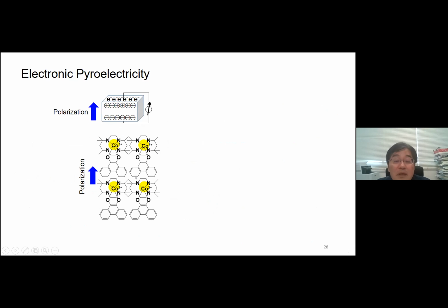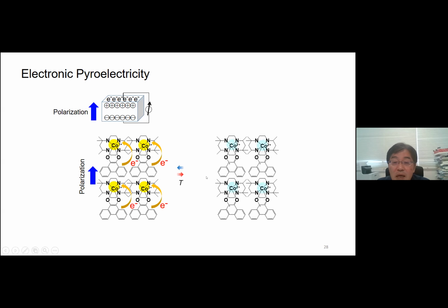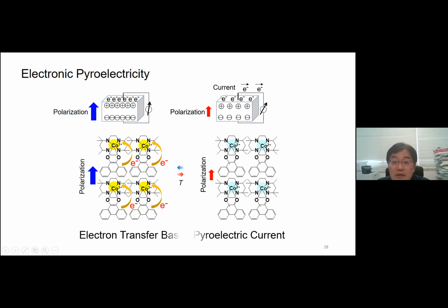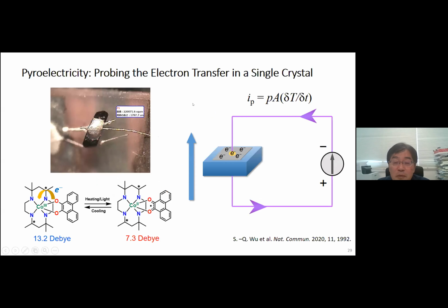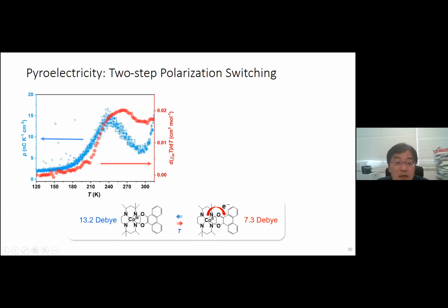And we tried to measure pyroelectricity. The low temperature phase is cobalt-3, so it has large polarization. On heating, electron transfer is induced and it becomes the cobalt-2 state, and its polarization is smaller than this one. Therefore, this change is detected as current. So we investigated the pyroelectric property using this single crystal. And this is the result.